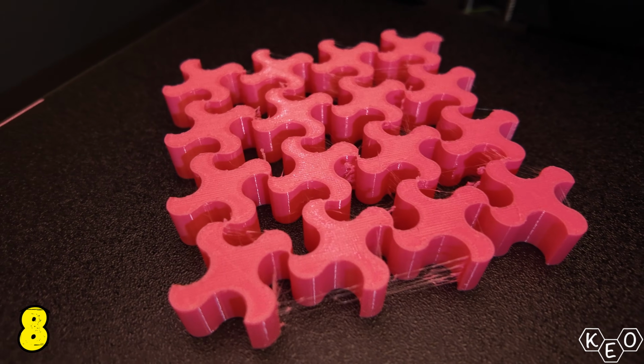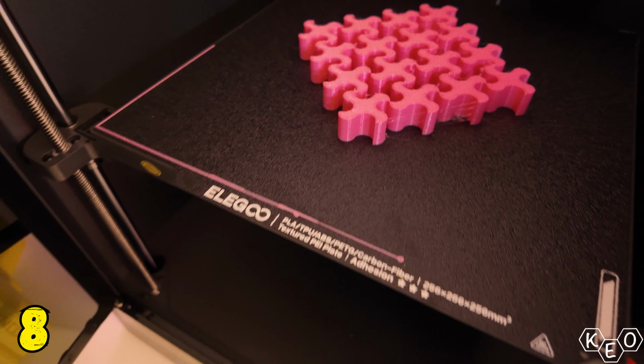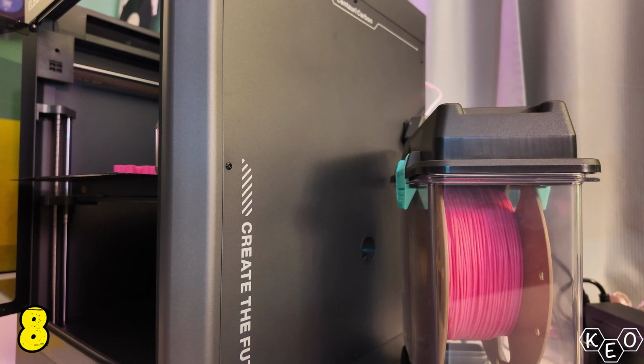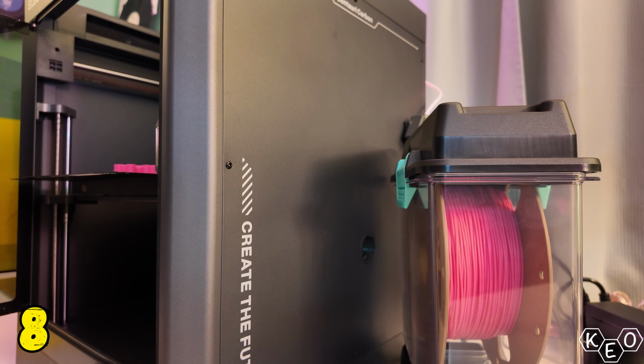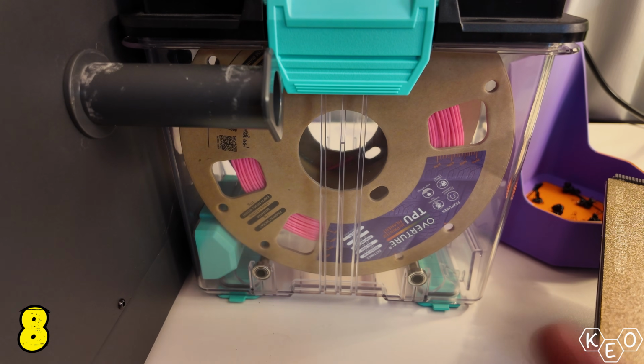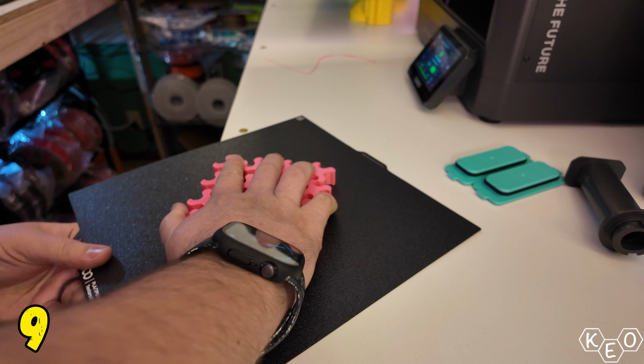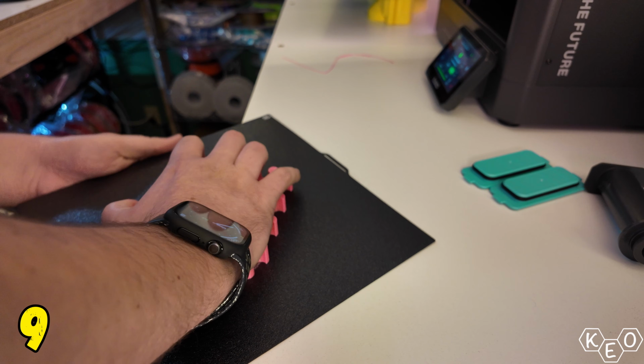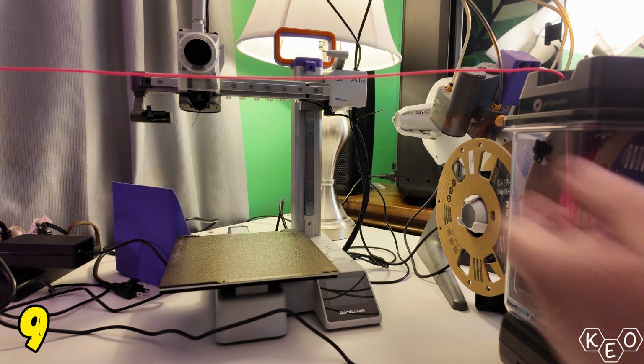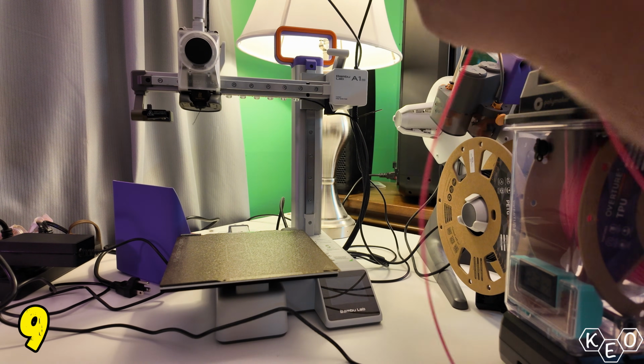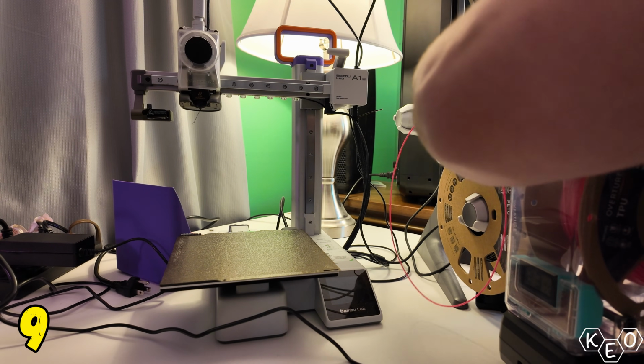This is what this pink Overture TPU looks like when printing on standard settings using the Elegoo Centauri Carbon. After drying it with the poly dryer for the recommended amount of time and reprinting, it looks much better. This spool had obviously soaked up a lot of moisture. But also, if you dry your filament and that still doesn't help the quality, likely there is a tuning issue. I thought this same pink TPU was wet, but in reality, the printer's default TPU profile isn't quite dialed in.